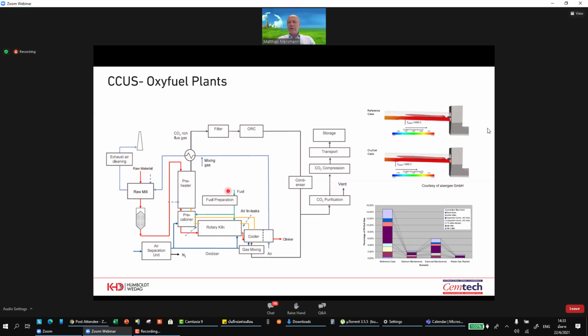And what's also necessary is to avoid false air from leaking in, because the nitrogen in the ambient air that is sneaking into the process will provide a contamination for the off gas, which you like to concentrate your CO2 to the maximum extent. So with a little bit of adaptation to the combustion machines like burners, and some other little devices, it should be possible also to retrofit technology to convert a conventional kiln plant into an oxy-fuel plant.